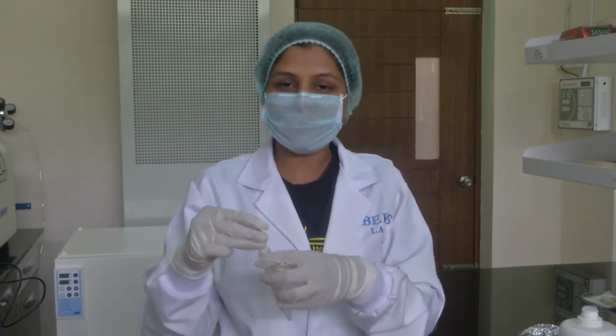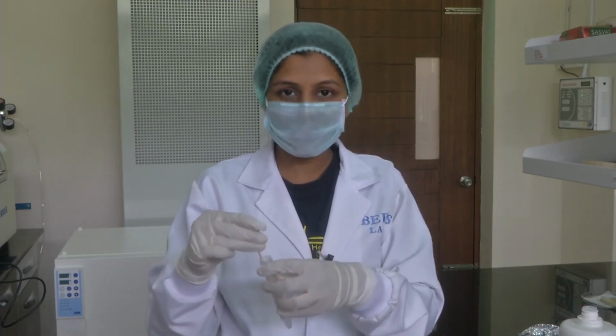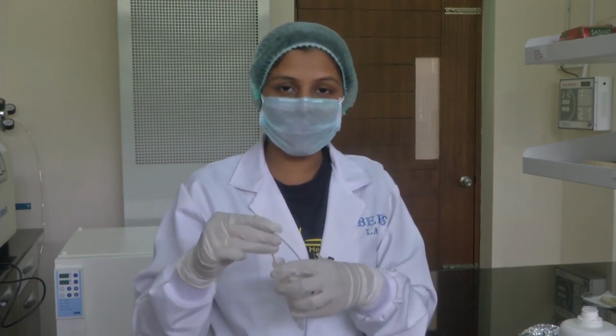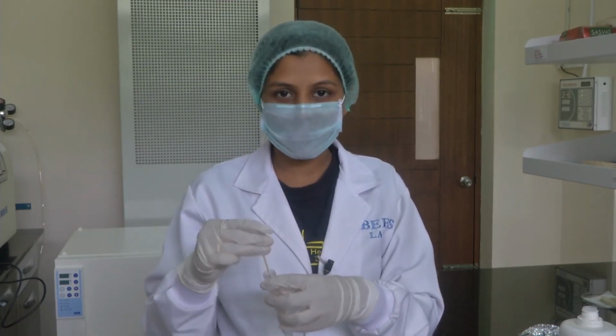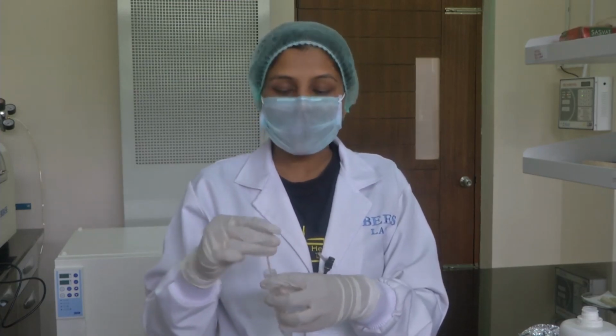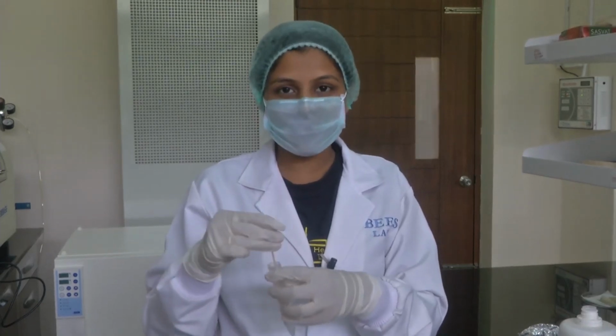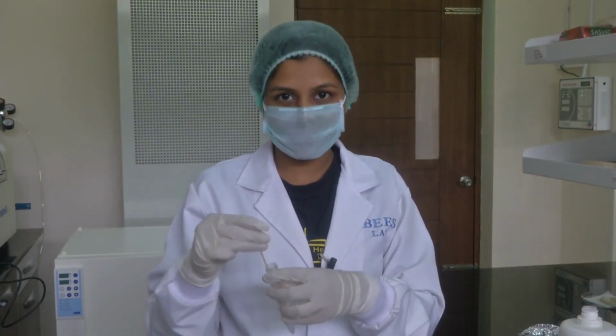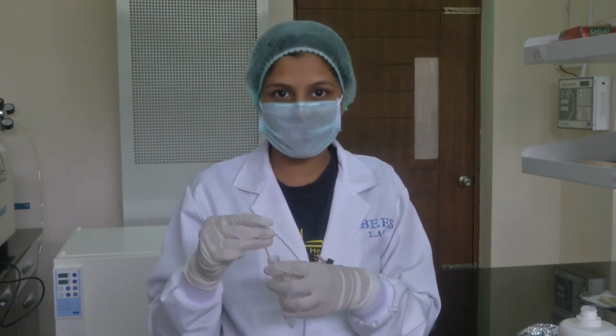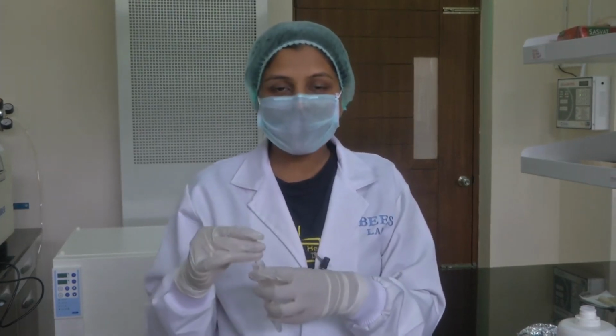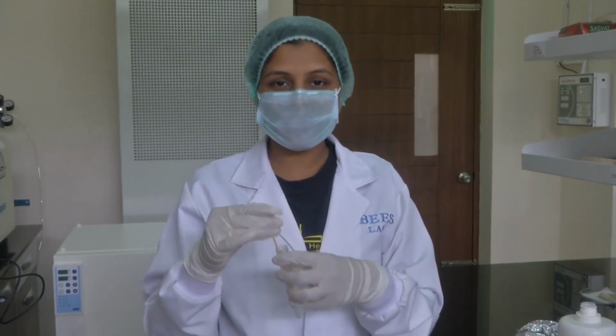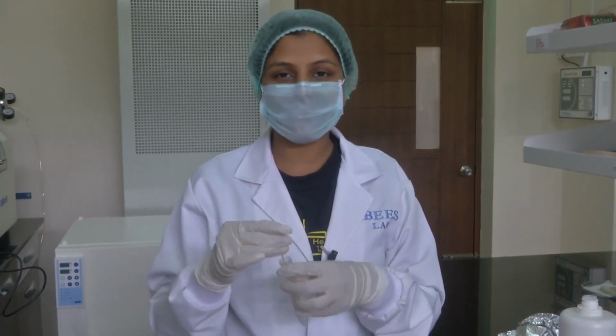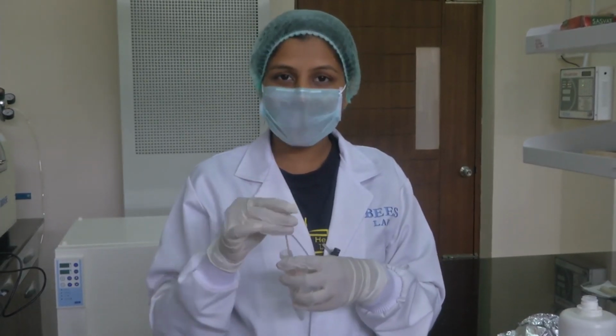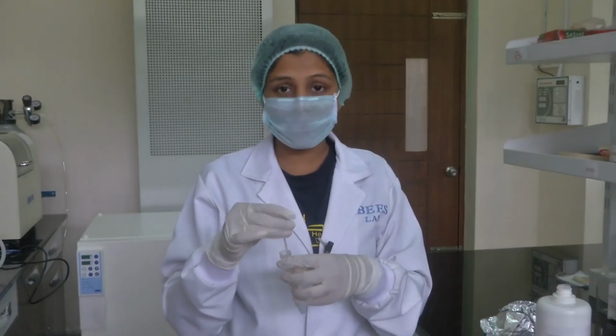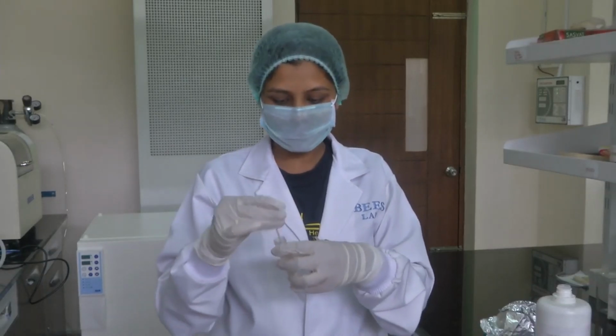What happens if you do not stir them well and you just use it on your mold and then cure it? Later you would see cracks, and they become more brittle. So it is not a flexible elastomer. When you cure it and remove it from your mold, you will see that they are more brittle and they tend to break even before you dice them in order to get your device.